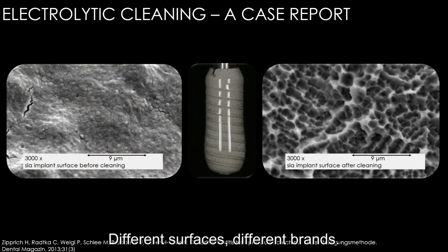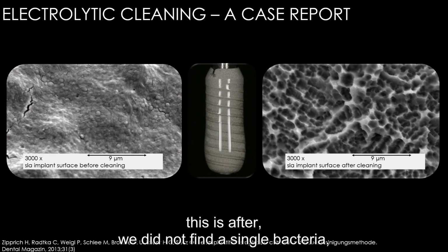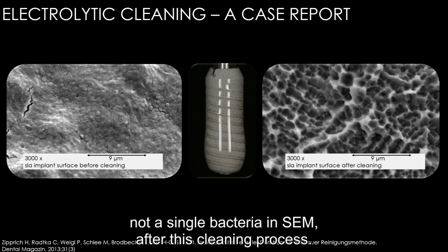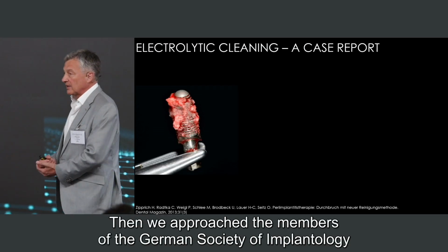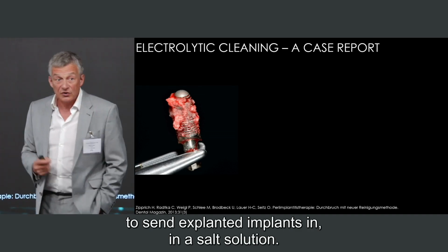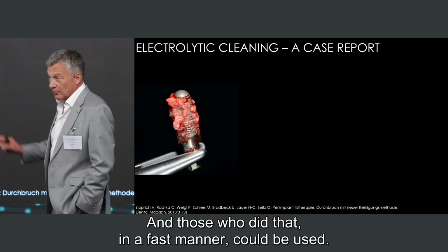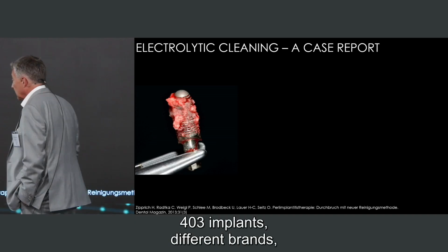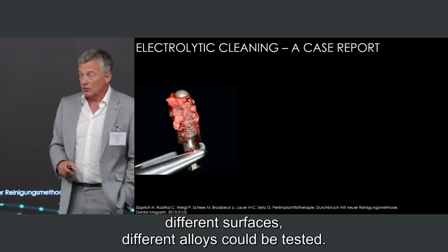Different surfaces, different brands. This is a typical situation before cleaning. This is after. We did not find a single bacterium in SEM after this cleaning process. Then we approached the members of the German Society of Implantology to send explanted implants in a salt solution, and those who did that in a fast manner could be used. 403 implants, different brands, different surfaces, different alloys could be tested.